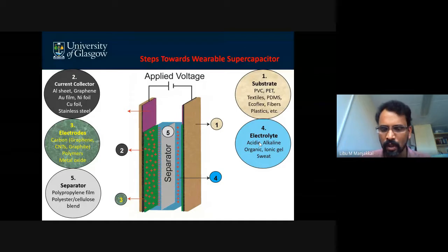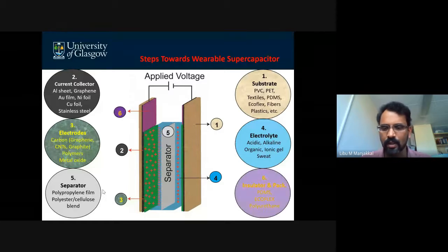So you have two types of electrodes, and in between those you fill the electrolyte. First you use a separator. That separator can be a polypropylene film or a polyester cellulose blend. I mainly use the polyester cellulose blend. Many materials you can use as a separator. So the two electrodes are separated with a separator, and then you drop in an electrolyte. Then finally you can make the packaging. And you have two electrodes, which you connect to the outside.